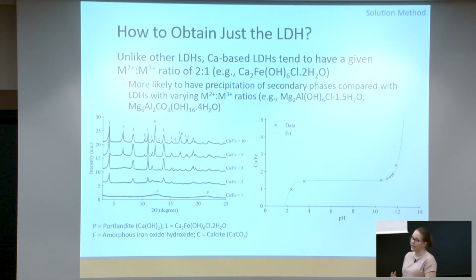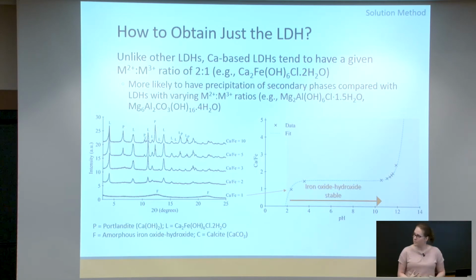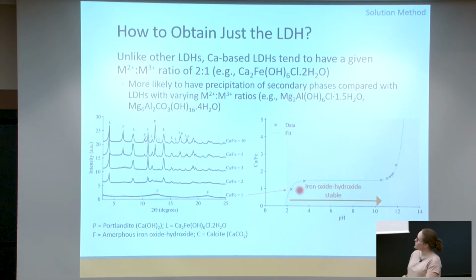And you can see there's very nice agreement. So if we go back to our experiments and look at what's formed, if we've got this ratio of 1, then the pH is too low for the layered double hydroxide to form, and all that we have is this iron oxide hydroxide phase. If we start with a ratio of 2, we're now in the region where the layered double hydroxide is stable. So we end up with some of that forming, but we still have that amorphous contribution from the iron oxide.